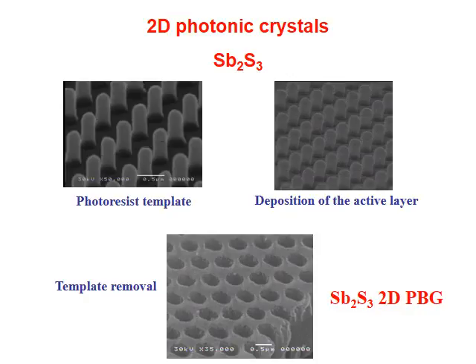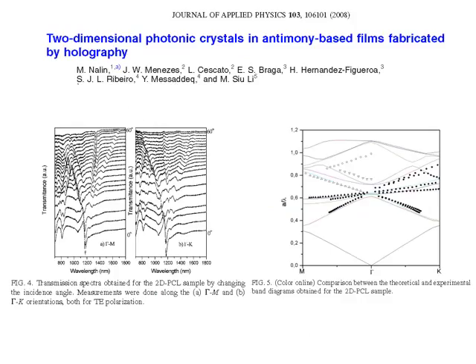Such materials present high refractive index that can be tuned from 1.8 to 2.4 depending on the film composition, the ratio of sulfide to oxide. The good quality of the obtained samples allowed the measurement of their PC properties through the well-defined funnel resonances that appear in the transmittance spectrum measurements at different incidence angles, as shown in the figure. The experimental results are in good agreement with the calculated band diagram for the hexagonal asymmetric structure.